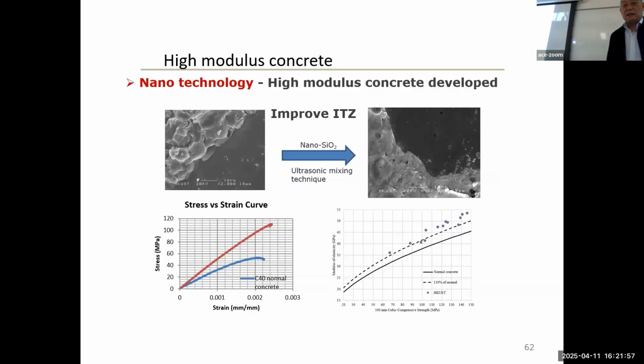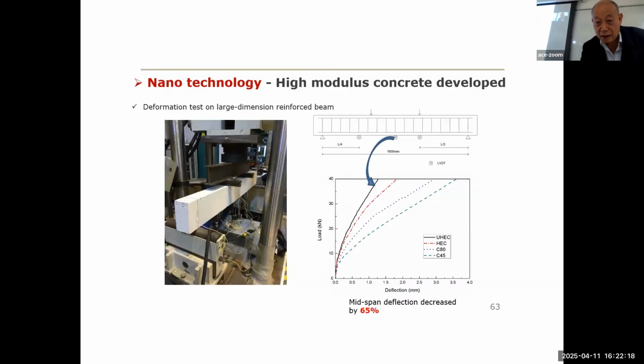And then what we found, by adding these nanoparticles, you can enrich the interfacial transition zone, and you can increase the modulus to about 53.5 gigapascal. And if you do the structural test, the beam midpoint deformation for the high modulus concrete is about 1/3 of that of the normal concrete. So here is a video.